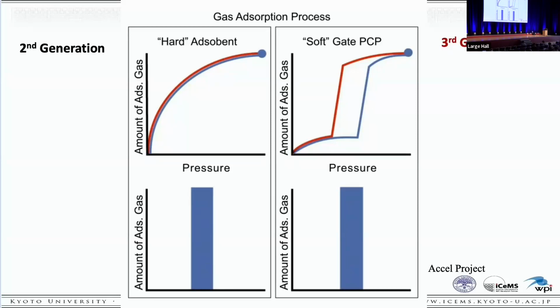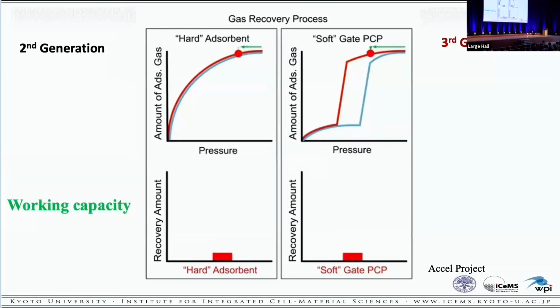Note that the amount of saturated adsorption remains the same. But if we look at the amount of desorption, on the other hand, there is a big difference in the recovery process. The adsorbed gas can be taken out at a certain pressure without bringing it to a vacuum state. In other words, there is a big difference in the working capacity. This is one of the advantages of the flexible system.